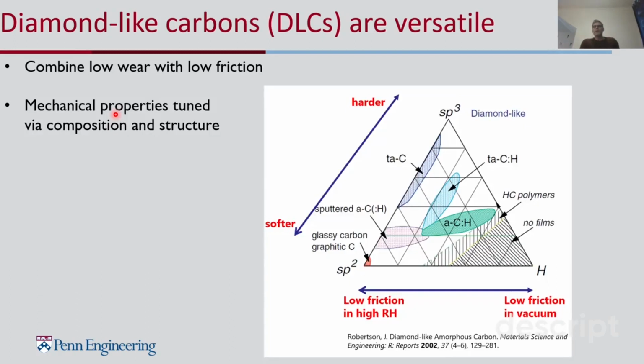And so one way that's been understood for a long time is that the response is controlled by two important parameters of the film structure. This ternary phase diagram tends to summarize this, and we have hydrogen on the x-axis down here. And films that are very high in hydrogen have low friction in inert environments, and if they have low hydrogen, you tend to need a reactive environment, typically water vapor, to have low friction.